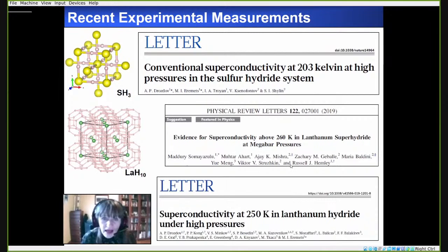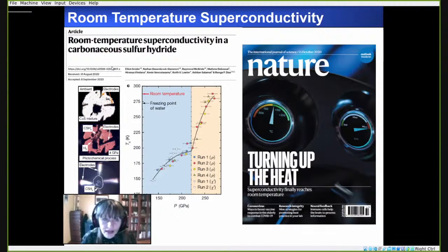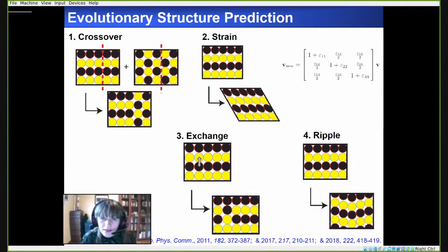Most recently, there has even been the discovery of room temperature superconductivity in an unknown phase that contained carbon, sulfur, and hydrogen. And here I show the pressure versus Tc plot. So we can see that the highest Tc achieved was at about 260 GPa, and it was almost at room temperature. However, the identity of this phase is still somewhat unknown. So how do we predict these very strange phases?